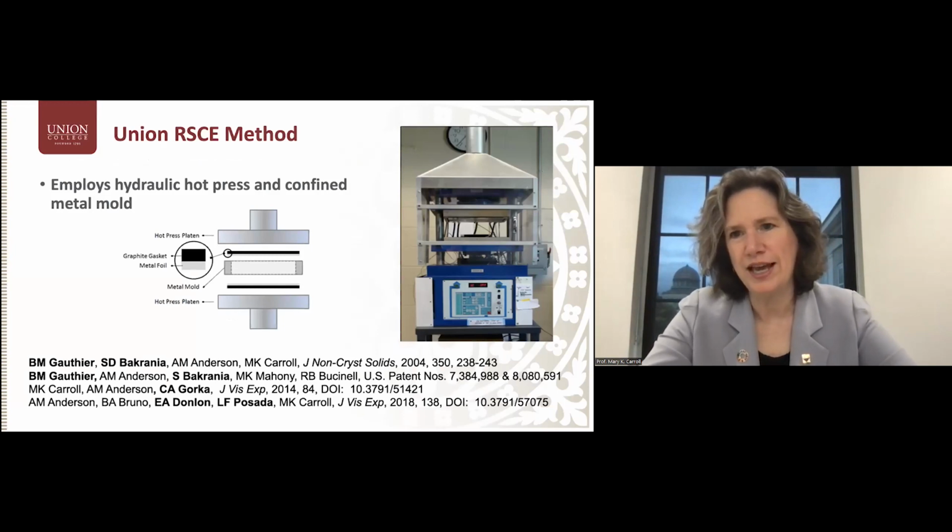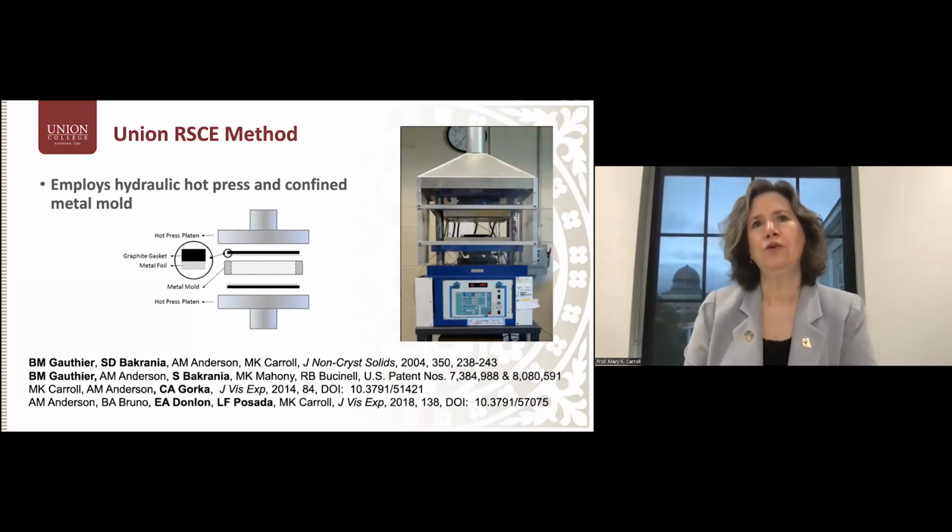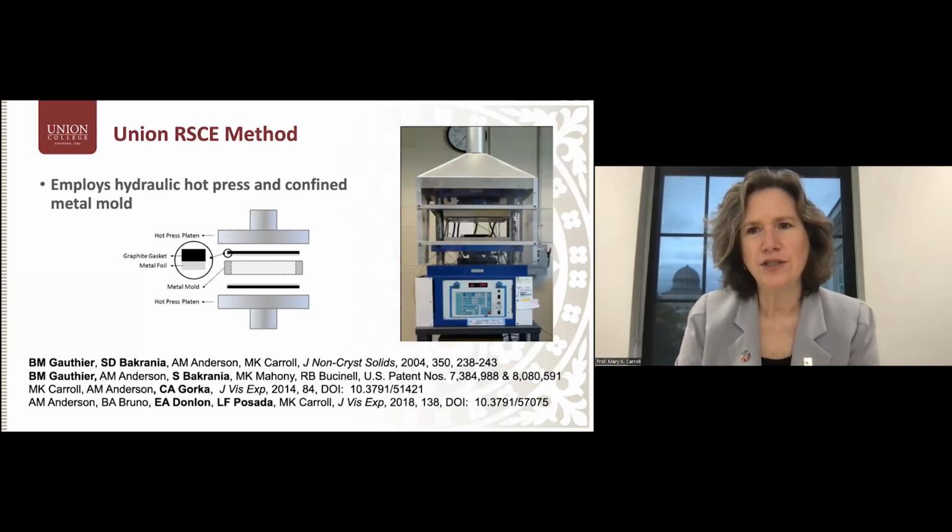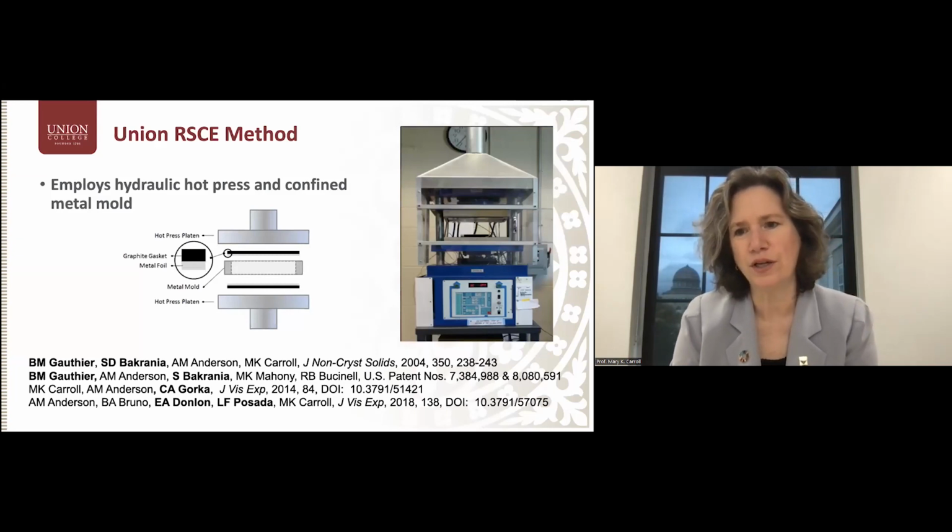And we've also been looking at whether changes in hydrophobicity occur over time. So we've just finished that. We haven't published the last part of it, but we did essentially 20 years of artificial aging. We do see some changes, but a window lifetime is thought to be on the order of tens of years. So 20 years seemed a reasonable time. The materials remain monolithic. That isn't the issue. It's just a question of whether some of their physical properties change.